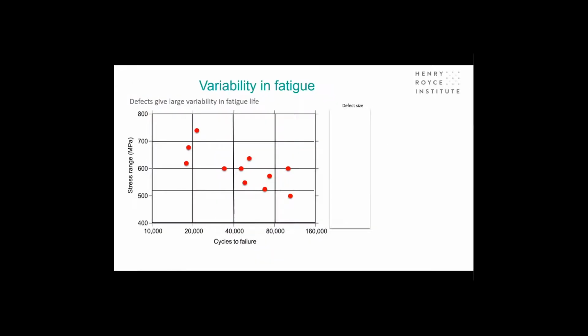Why is it important? It's important because defects control a large number of properties, and perhaps one of the most important is they can lead to a very large variability in fatigue. If you look at this SN curve, which shows the dependency of the number of cycles to failure on the stress range, you can see that whilst it's true that the increasing stresses lead to shorter lifetimes, a huge scatter is observed in the data. And that is because of the presence of defects, and those defects are stochastic in nature, and so that leads to a stochastic variability in the fatigue life.